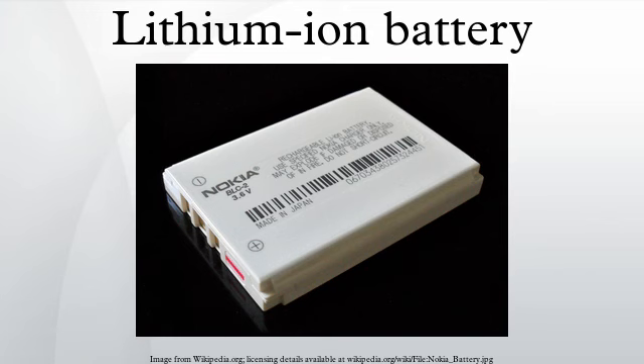In 1996, Goodenough, Akshaya Padhi and co-workers proposed lithium iron phosphate, LiFePO4, and other phospho-olivines as positive electrode materials. In 2002, Yet-Ming Chiang and his group at MIT showed a substantial improvement in the performance of lithium batteries by boosting the material's conductivity by doping it with aluminium, niobium and zirconium. The exact mechanism causing the increase became the subject of widespread debate.